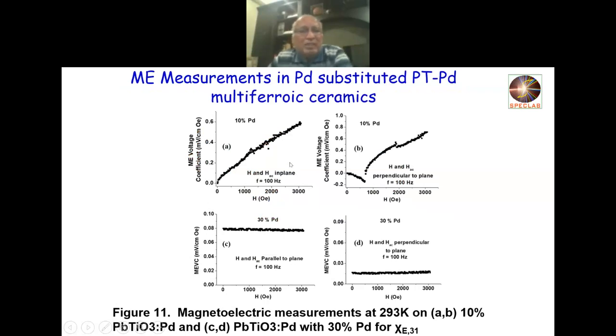We did again the magnetoelectric measurements in this material. These are all ceramics so far. So the magnetoelectric measurements did give some magnetoelectric coefficients, something like 0.4, 0.6. That's the maximum you could get in the 10%. And for the same thing, we got something like 0.08, a very small value. The magnetoelectric coefficient was smaller compared to what I have shown you earlier, the solid solution materials.